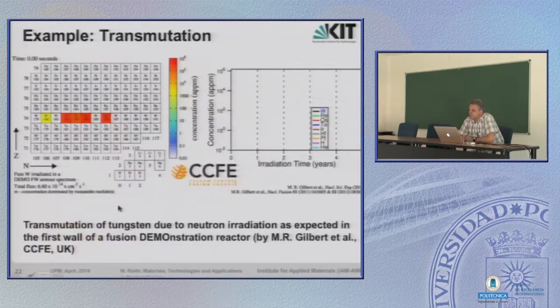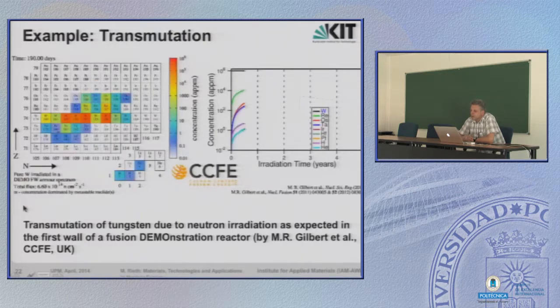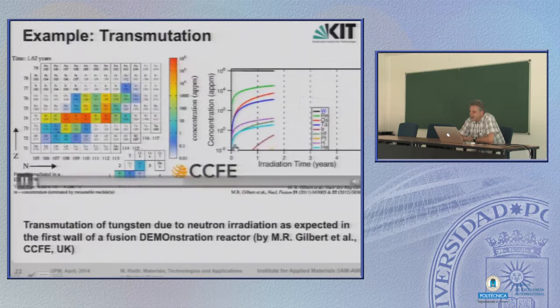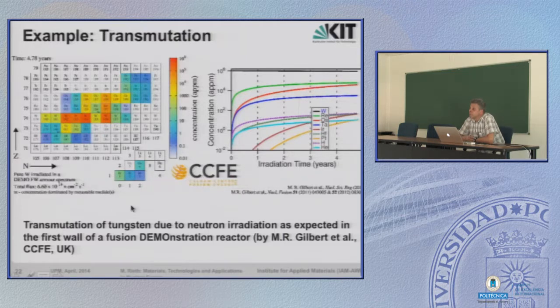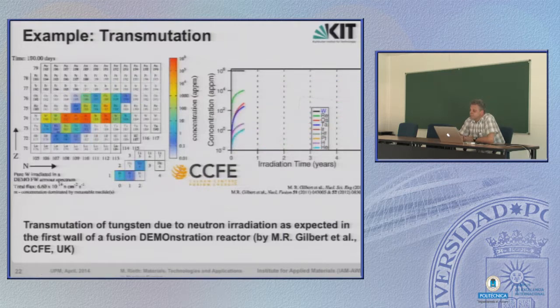This is an example of transmutation of tungsten in a fusion reactor. I said the first wall will be made, or has to be made, of tungsten due to various reasons. So you start with naturally available tungsten, and that's a mix of these five tungsten isotopes. In this row, we have all the tungsten isotopes. The next rows are tantalum and so on, hafnium, lutetium. And if we start with the reactor working, you see how a variety of different other elements are produced and how they develop in different amounts in the periodic system. So you start with pure tungsten, and after 5 years,